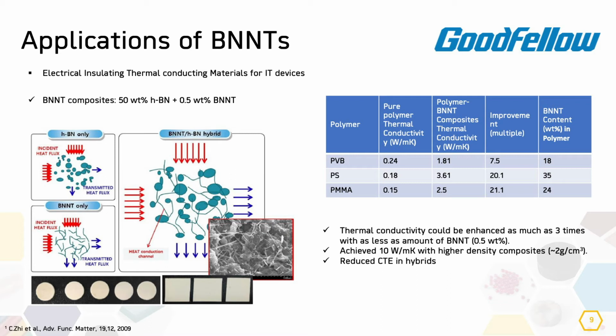By this, we can see that we have embedded them in different matrices like the polyvinyl butyral, polystyrene, or PMMA, and we have enhanced the thermal conductivity. I will say that it's as much as 3 times higher than the pure polymer. Also, what I would like to say here is that the coefficient of thermal expansion of the hybrids has been reduced because of the interactions between the polymer chains and the boron nitride nanotubes.